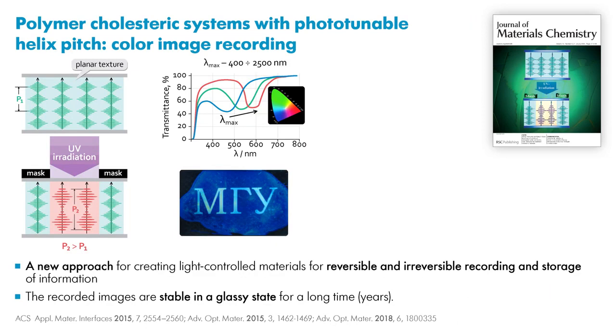This approach allowed us to record color images. For such recording, polymer films were irradiated using a mask. We have observed a shift in the peak of selective light reflection to the long wavelength spectral region. The magnitude of this shift can be very large. We realized the position of the peak from 400 nanometers to 2500 nanometers, and in our case, it is limited only by the spectral range of our spectrometer.